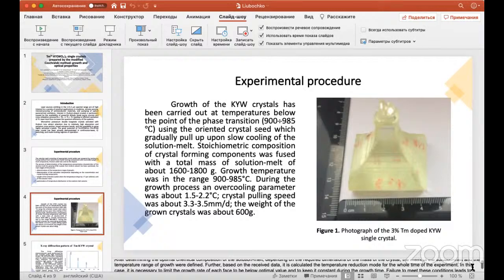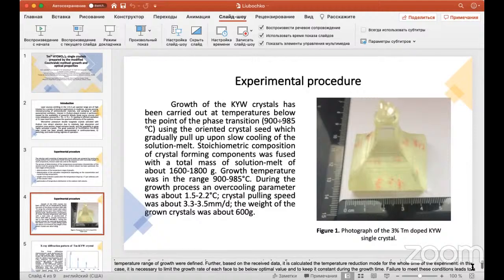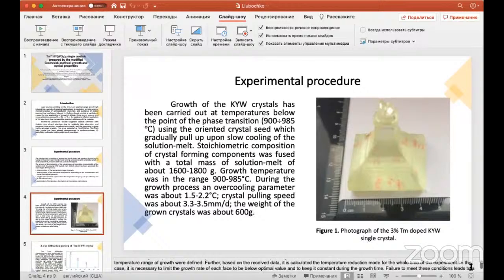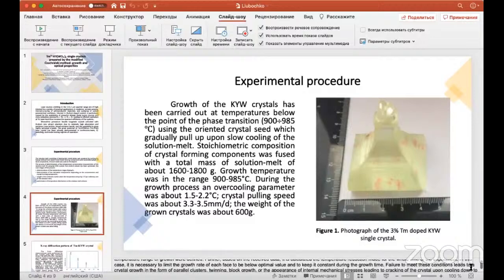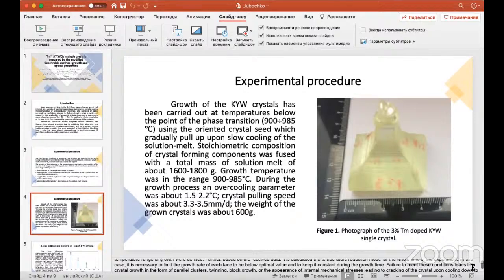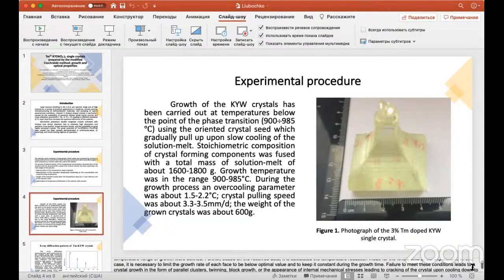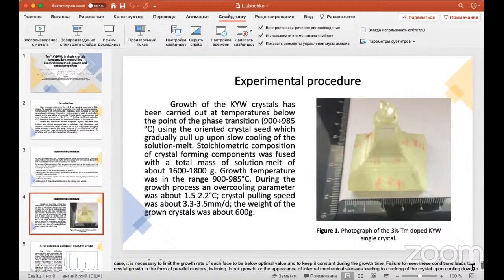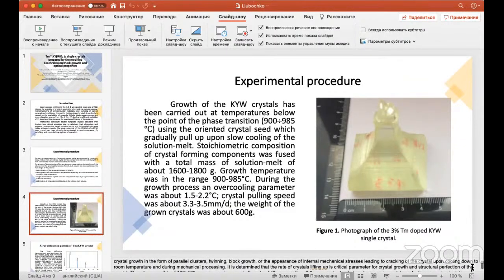In this case, it is necessary to limit the growth rate of each face to be below the optimal value and to keep it constant during the growth time. Failure to meet this condition leads to crystal growth in the form of parallel clusters, twinning, block growth, or the appearance of internal mechanical stress leading to cracking of the crystal upon cooling down to room temperature and during mechanical processing.